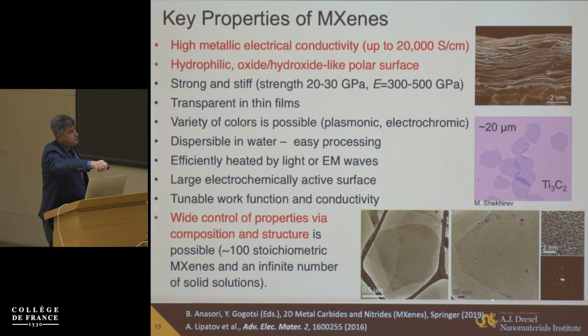Otherwise, they look like other 2D materials. They're single crystalline. You can see it from high-resolution TEM and from selected area diffraction. And you can assemble them into this multilayer film. The film I showed you before, a long stripe 10 centimeters wide and a meter and a half long, would have a structure like that. This one will be freestanding, probably about 6 microns, so you can handle it like a thin paper. Again, this dispersibility in water is important. They're also plasmonic materials, and there are a lot of tricks you can do with them. There are many other useful properties which I'm not going to discuss today, like a chemically tunable work function and conductivity.